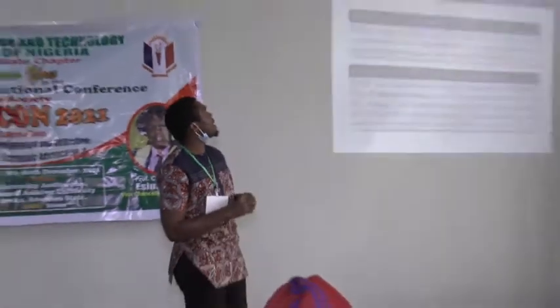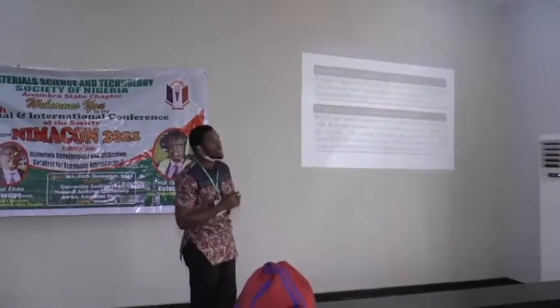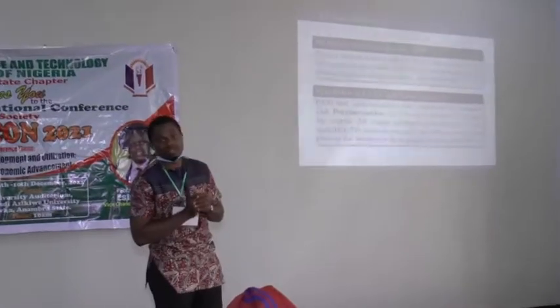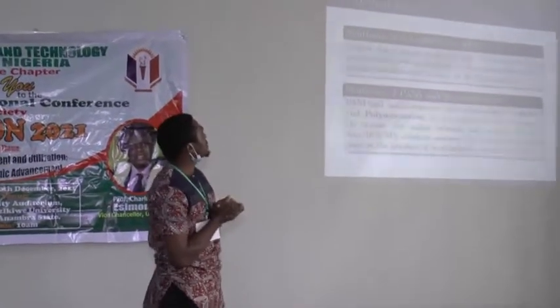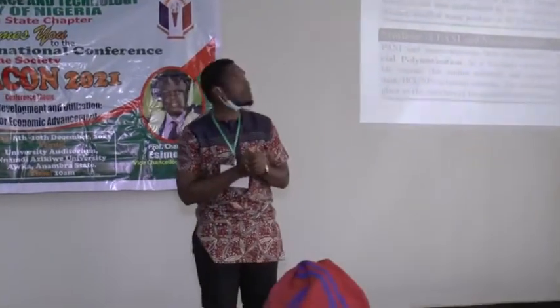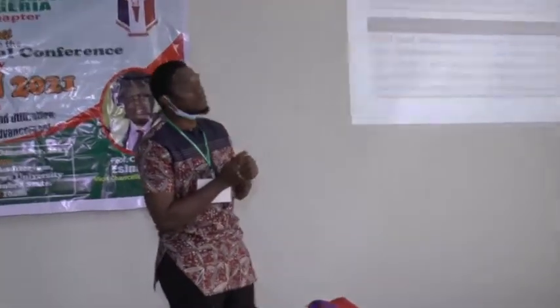Now, the methodology. The nanoparticles, we synthesized 2 nanoparticles, that's the 5% copper doped and 15% copper doped, by way of chemical method in ethanol distilled water mixture at 80 degrees for 3 hours. After the synthesis, the product was washed with distilled water and calcined at 300 degrees for 2 hours.